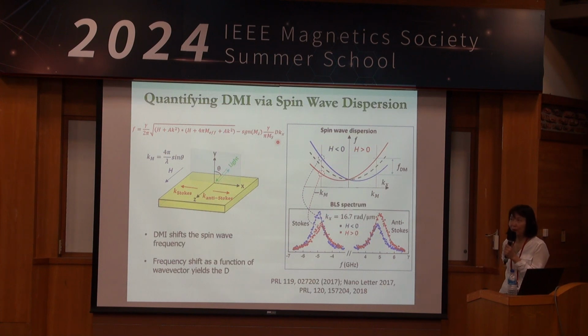The probe spin wave typically is actually related to the size of the structure I'm measuring, because the physical structure also basically breaks translational symmetry. So the momentum conservation is only approximately conserved in that whole process. Okay, so I had a long conversation with my group about this. Nobody wants to give up momentum conservation, but you have to understand it's actually a result of translational symmetry.